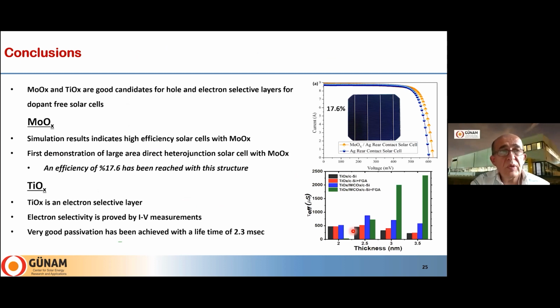Well, for the conclusion of this part of my talk, we have analyzed the use of molybdenum oxide and titanium dioxide as electron and hole selective layers for heterojunction solar cell technologies, and we see that molybdenum oxide is a very promising material. We fabricated solar cells using that, so we can avoid doping, we can avoid the use of toxic gases, and these materials can replace the doped amorphous silicon layer in the heterojunction technology.